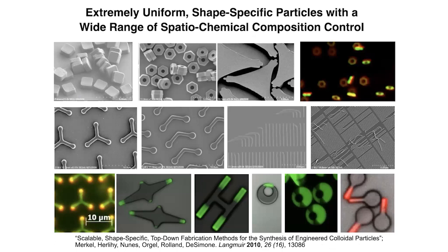And so this whole idea in a roll-to-roll process that we could have a mold almost like an ice cube tray from the micron scale down to the nanoscale, and we could fill that unique cavity to make a reactor out of it on that length scale, chemically convert the liquids into polymers, and then we could remove those particles as particles with controlled size, controlled shape, and most importantly, controlled chemistry. And not only controlled chemistry, but spatially trying to control where certain chemistries were within particles. And this whole area of functional colloids and putting these kind of particles into new environments and the like was a fun run.